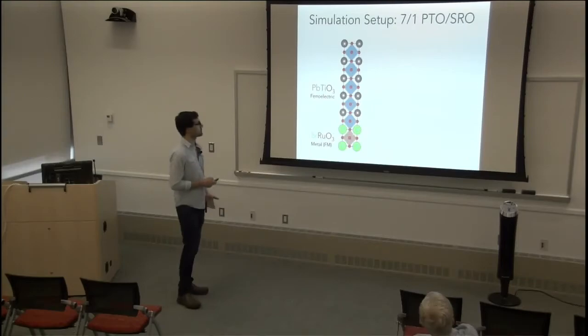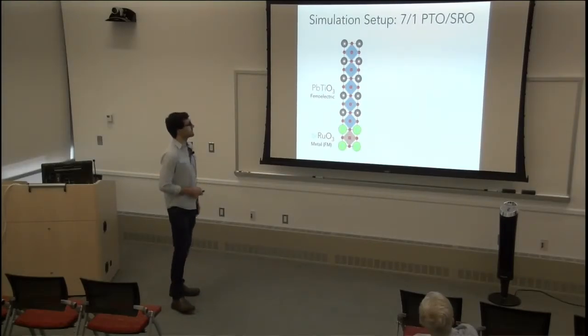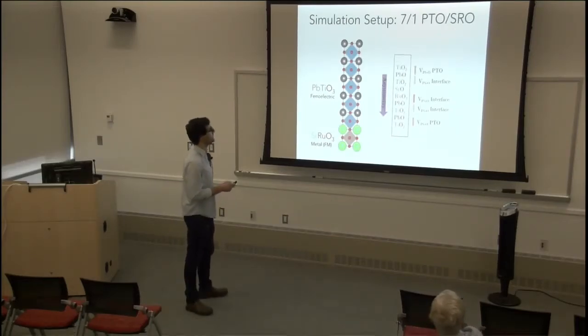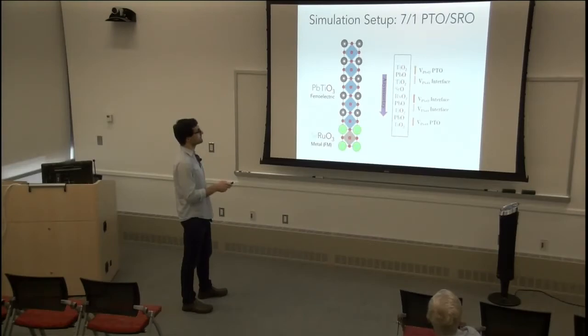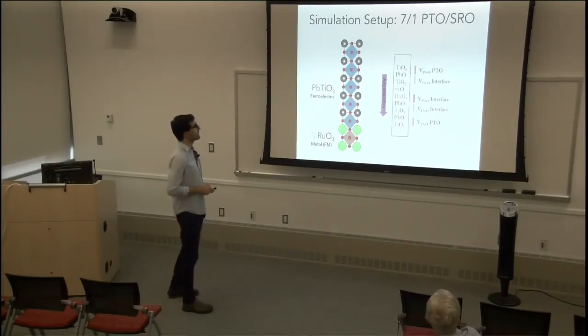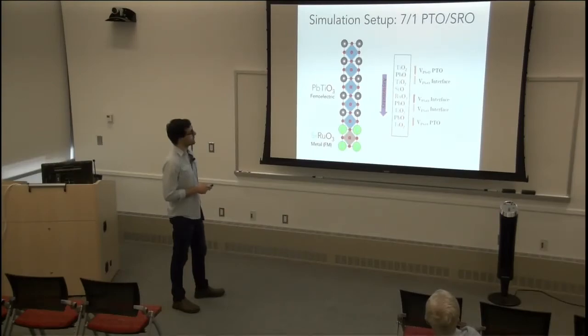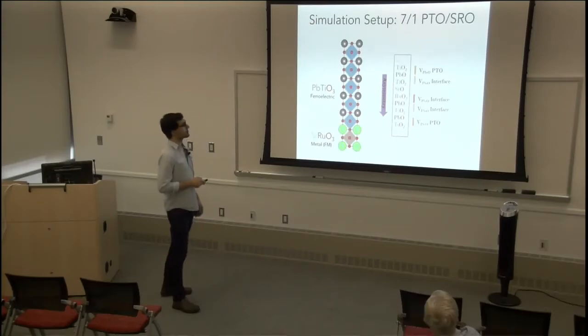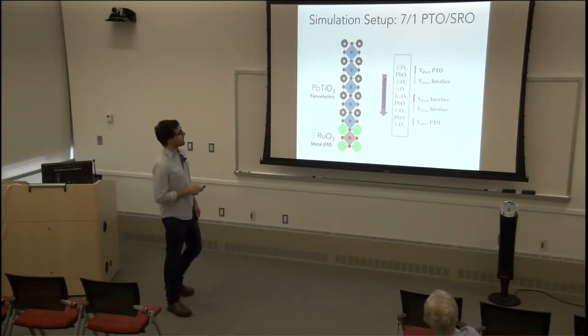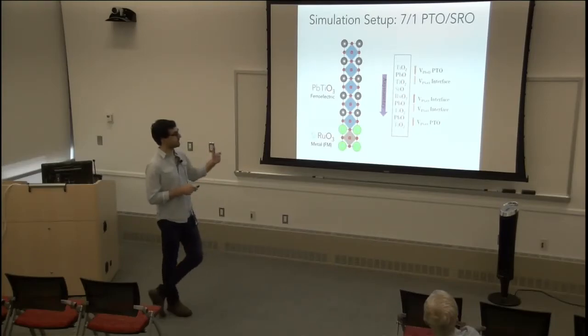And you might say, well, okay, it's just as simple. You have one here, right? But it turns out it's more nuanced than that. Here I write the layers, the titanium dioxide, lead oxide. Here I have the strontium unit cell. And because if you think about the strontium oxide as a mirror plane, you see that there's no mirror symmetry over this plane. Instead of having a titanium dioxide, as you would have in strontium titanate, lead titanate, you have a ruthenium dioxide. And because you don't have this mirror symmetry, you get a preferred state because of the asymmetry at the interface.